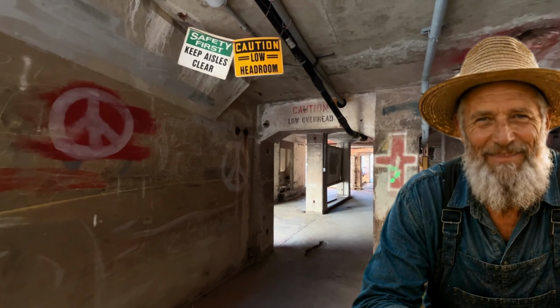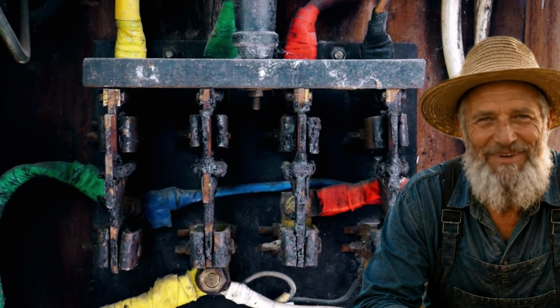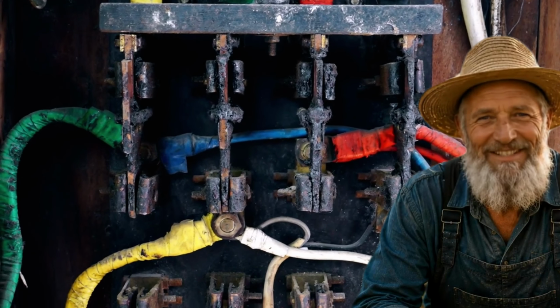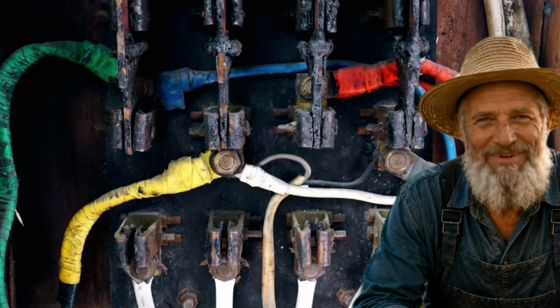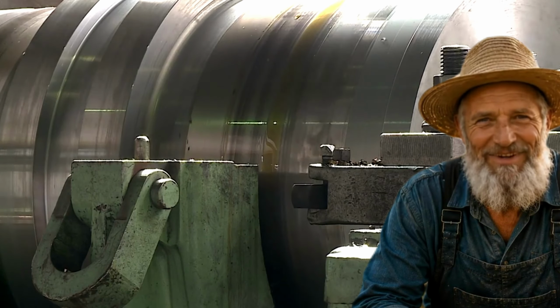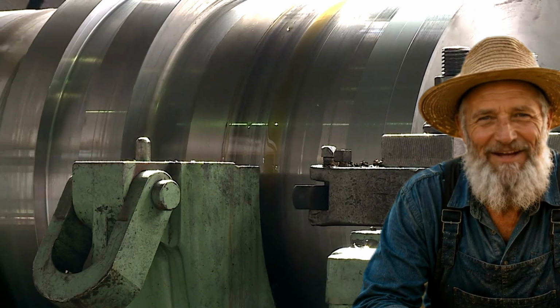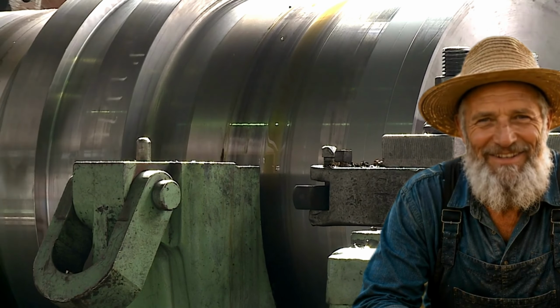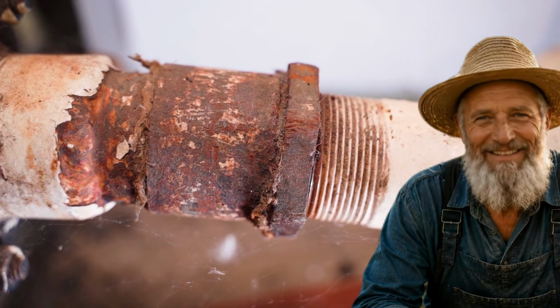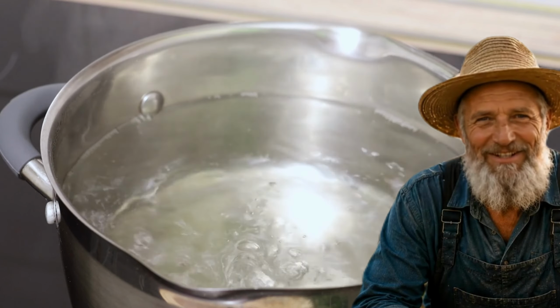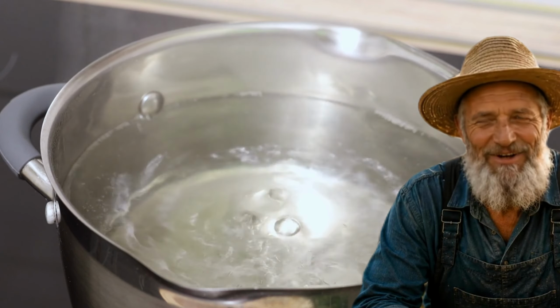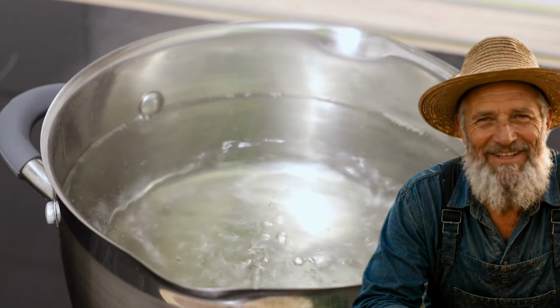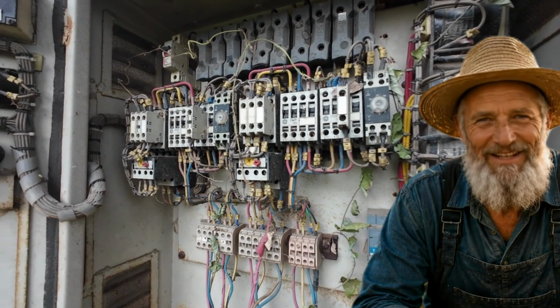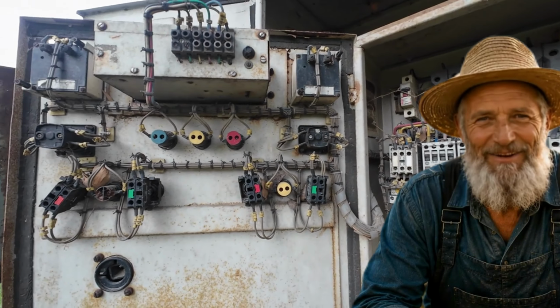Stay with me. Because what I found in Holmes County and a 2002 federal report uses the same chemistry older metal cultures used against oxidation. The hidden trick is simple. You do not have to remove every atom of rust to stop the damage. You have to break the reaction path. When water forms a thin film across steel, oxygen and dissolved salts start moving charges across the surface. That is why the same car can look clean on top and rot from the inside out below the trim line. Rust is an electrical event wearing a dirty orange disguise.